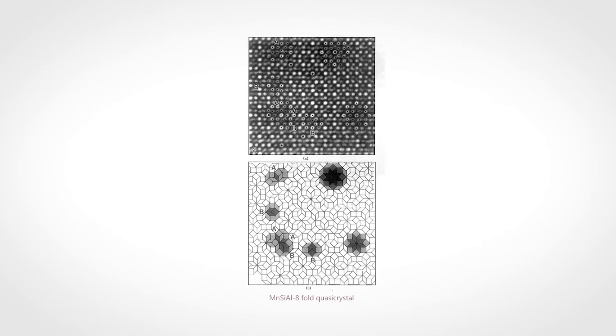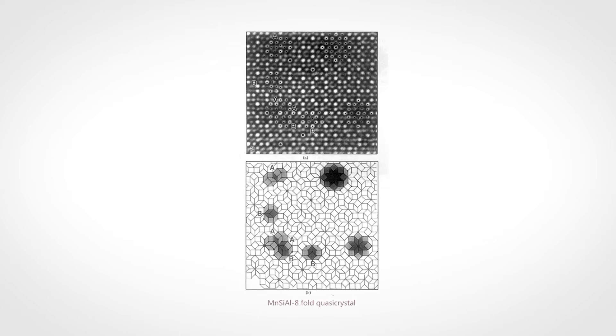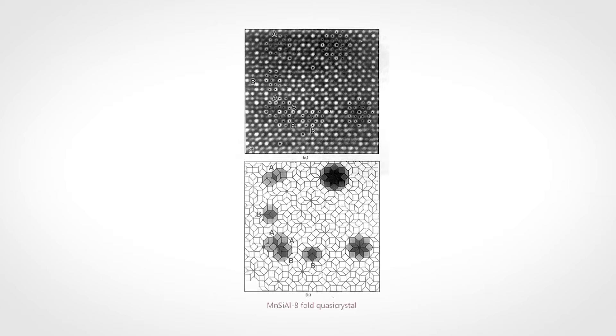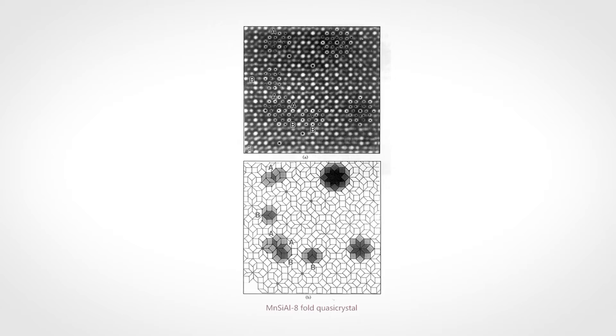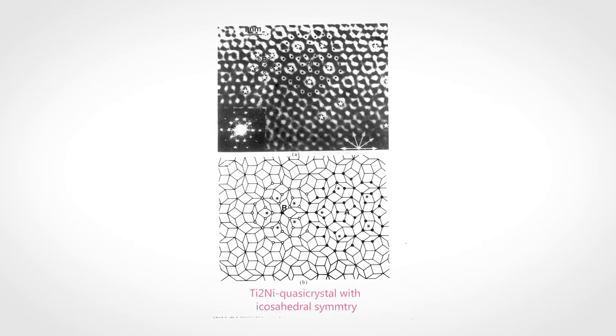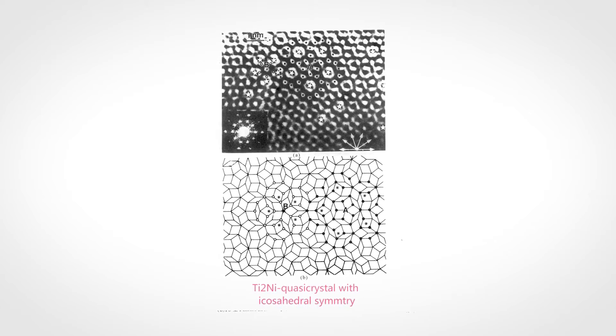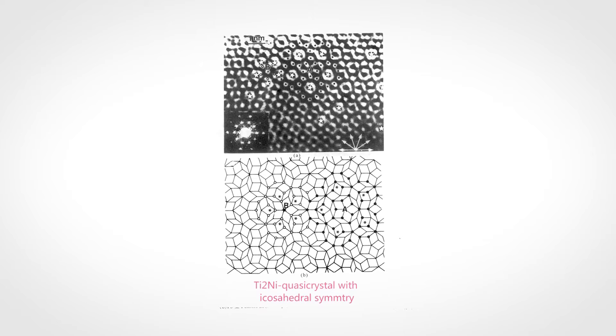The main problem of material science is to understand the relationship between microstructure and performance. We have found many new phases and new structures. For example, many years ago, we observed a fivefold symmetry phase in titanium, vanadium and nickel alloys. Such fivefold symmetry is not allowed in bulk crystalline materials.